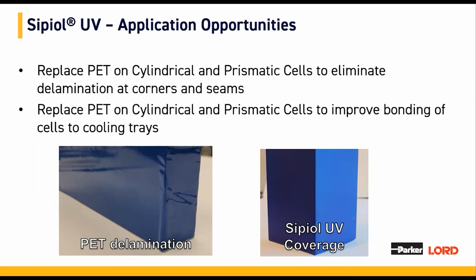Sipiol UV can be used as a PET film replacement on cylindrical and prismatic cells. Sipiol UV has superior adhesion to battery cells when compared to PET and will not debond or delaminate during use. This is demonstrated in the images on this slide. Note the delamination of the PET at the sharp corner of the prismatic cell. Preventing delamination and maintaining electrical isolation is vital to safety in high voltage batteries, and even more important as energy density is increased.